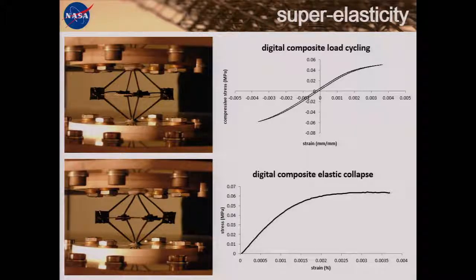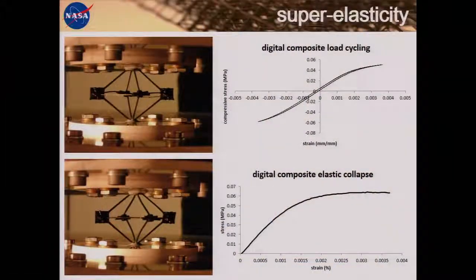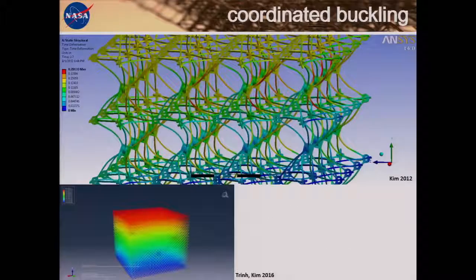there's this effect of twisting the free end nodes, transferring a substantial bending moment through these nodes, and you'll see from the strut spacing and the buckling of the struts that you have this coordinated twisting motion. And so throughout a large structure, this appears to develop into a coordinated buckling behavior that is something like a three-dimensional folding or pleating. This is also readily apparent in simulation work being done by Kim and Trinh. And the rotational displacements that develop for each node are antisymmetric relative to most of its neighbors.